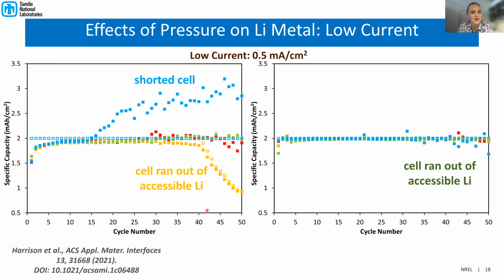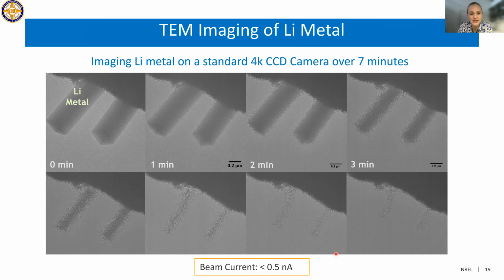This is lithium if you're imaging it inside of a TEM under more normal conditions. So a beam current of 0.5 nanoamps over several minutes. You can see here that the lithium actually just pretty much sublimates. It disappears because it's being broken down by the electron beam.